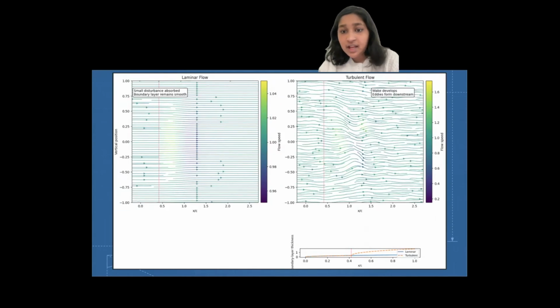But in the turbulent example on the right, you can see what would have happened if the layers had caused a problem. The lines get wavy, uneven, and start forming small swirls. Since my surface didn't cause those changes, it confirmed that the wing felt the same to the air, which is why the drag only increased by around 0.2%.